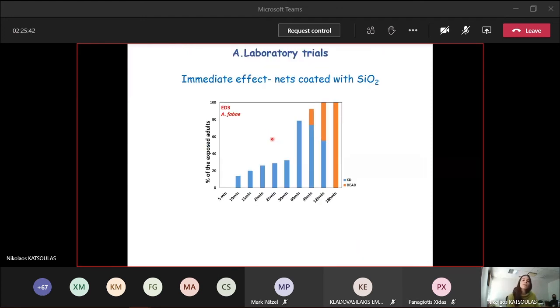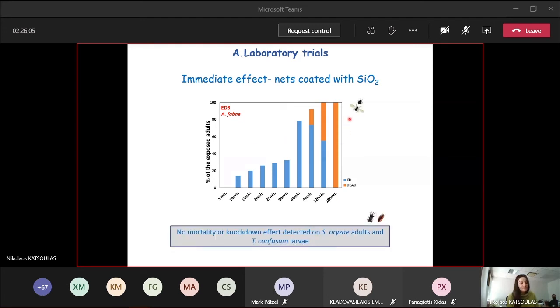Here in this graph, you can see that in the case of Aphis fabae, the most effective net was the net that was coated with the ED3 dust formulation. And here in this graph, you can see that 180 minutes of continuous exposure to this net led to 100% mortality of Aphis fabae. However, in the laboratory trials, we realized that there was no mortality or knockdown effect detected in the case of the stored product insects.